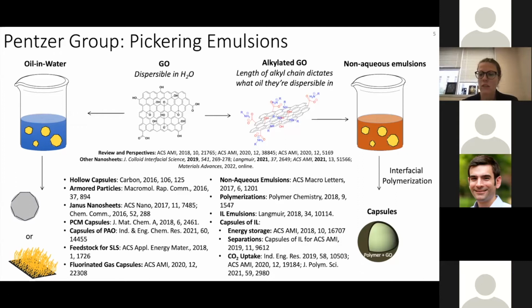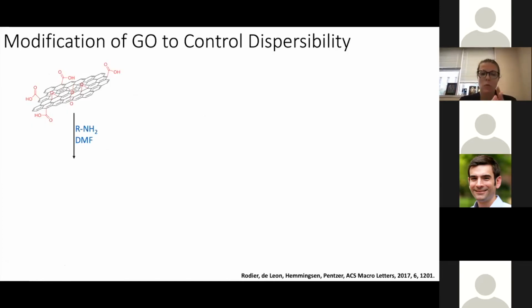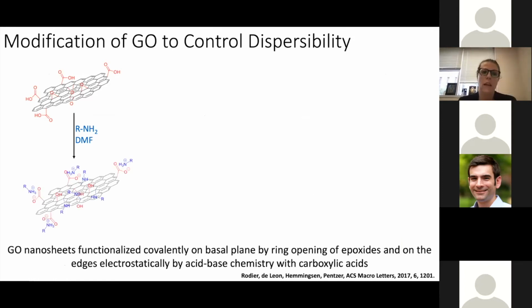And we can use this platform and polymerization at the interface to prepare capsules, which have a core of whatever liquid was the droplet, and then a shell of polymer and nanosheets that can be isolated by filtration. And so to change the wettability of the nanosheets, my first PhD student, Brad, looked at reacting GO nanosheets with primary alkylamines. The idea was we could get the ring opening of the epoxides from both faces of the nanosheets, as well as acid-base chemistry with the carboxylic acids on the edges.